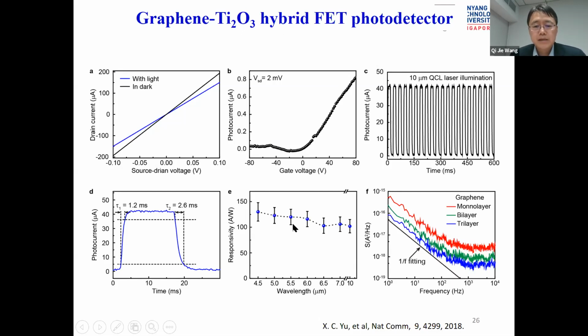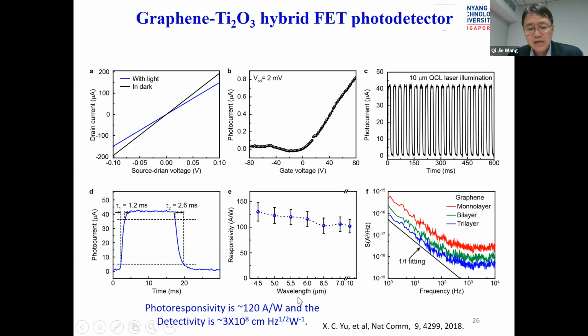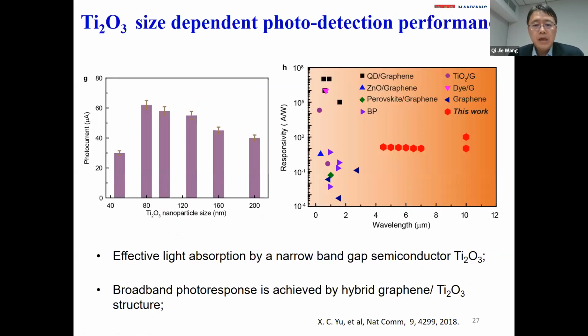This is limited by the laser that we have in the group, and we also characterize the noise level in order to determine the detectivity. So at room temperature, this can reach 3 times 10 to the 8, which is also, I would say, a reasonably good number as a start. And compared to other 2D material-based photodetectors, this type of device, to our knowledge, should be the first of such type that covers the mid-infrared region with good responsivity, shown here.